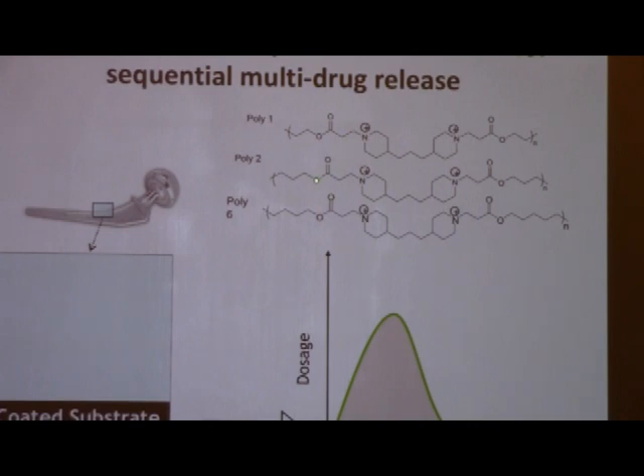I can change the rate of degradation of the polymer by changing what I put into the backbone. So these are polymers that degrade at increasingly slower time frames. I can layer that with, let's say, a negatively charged biologic drug.